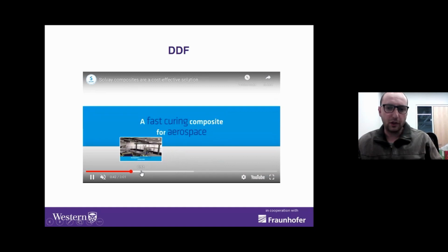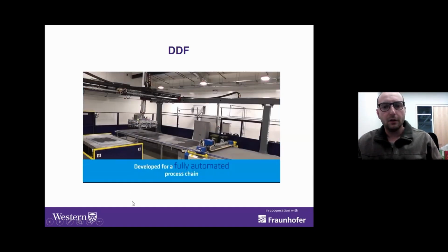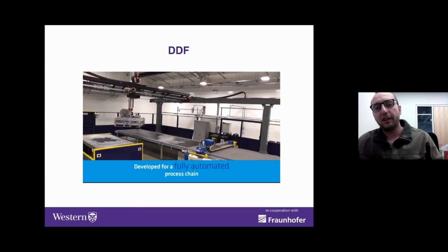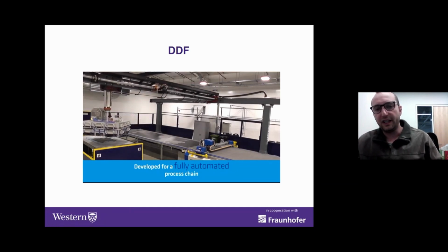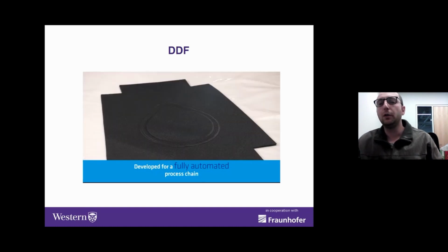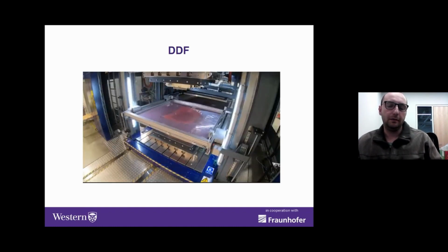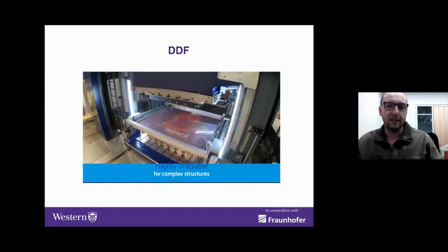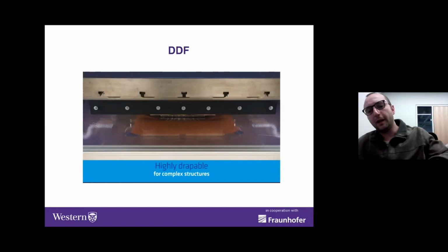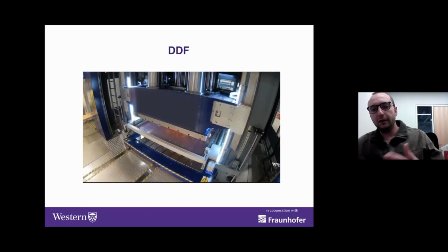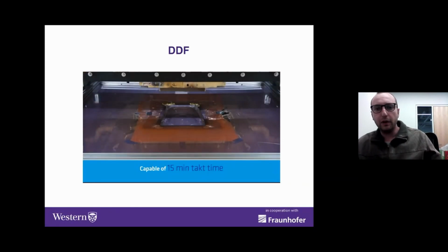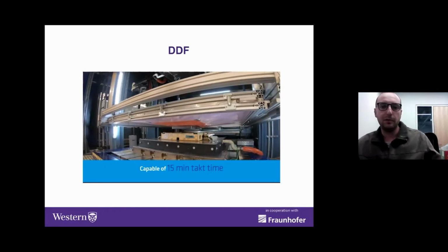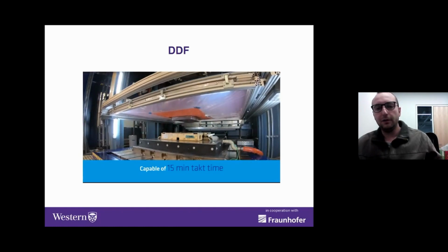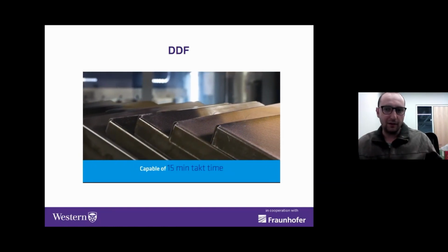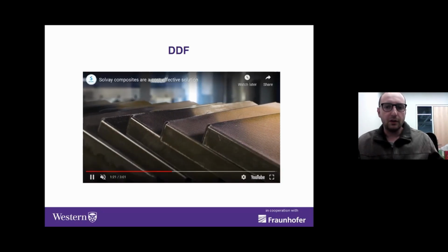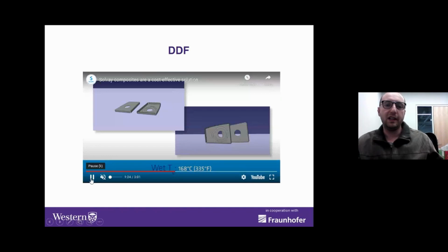So let's actually move to the actual process, which is here now. So you can see automated fabric cutting, then automated preform stacking. We actually had equipment like this at FPC for a while, and it wasn't used, so we disassembled it. And then this preform is moved automatically in the frame, in the mold, and now you can see how easy it is to demold it. You see, it just lifts it up, nothing stayed on the mold, very easy, fast demolding, and then you have your part. So it's a great technology for medium scale production.